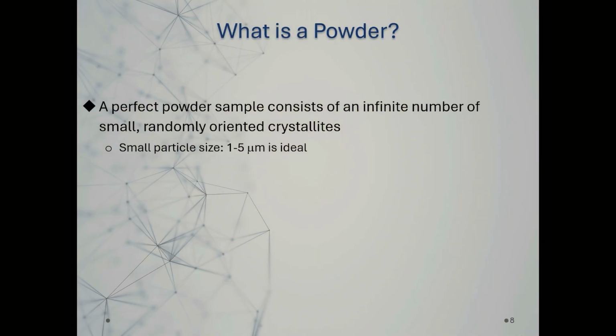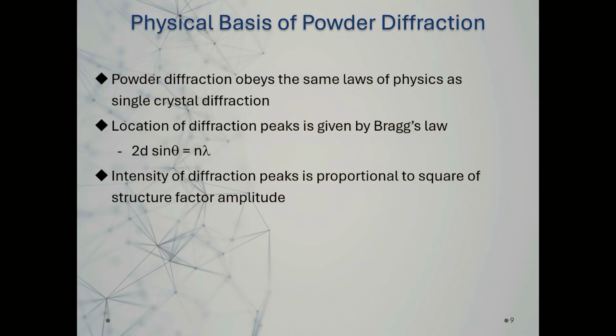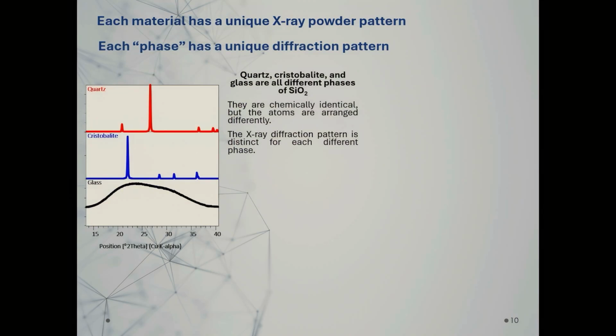But what is a powder? As you already have heard, a perfect powder consists of an infinite number of small, randomly oriented crystallites. So we are talking about a dimension of 1 to 5 micrometers. And in this case, we can speak of an ideal powder. And for the physical basis, I just repeat something that you already know. Powder diffraction obeys the physical laws of single crystal diffraction, the location of the diffraction peaks is given by Bragg's law, and the intensity of diffraction peaks is proportional to the square of the structure factor amplitude.